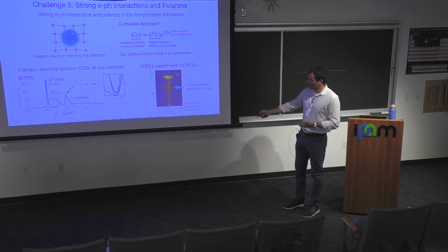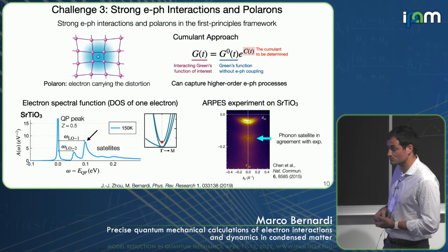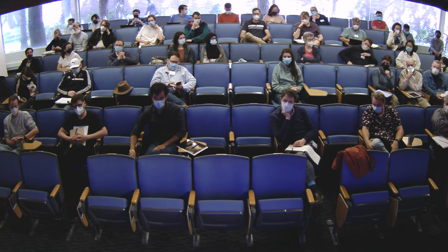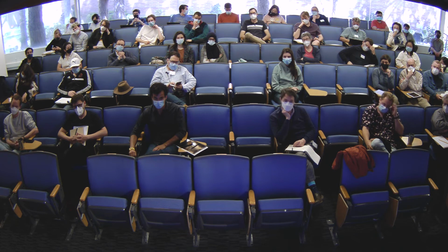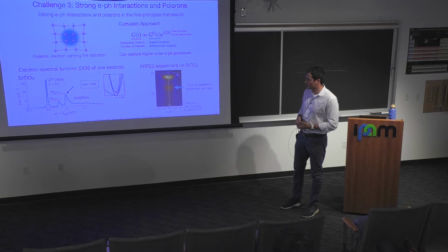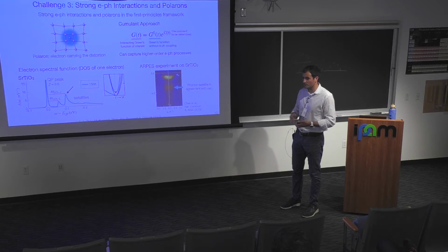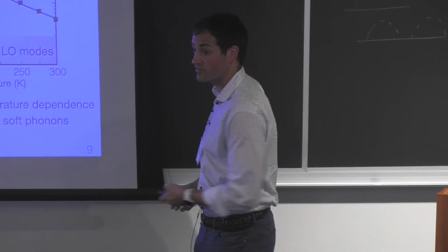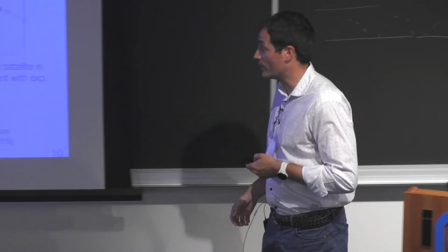But in general, these satellite peaks and their appearance here, this is usually a signature of the polarons. But you cannot really decompose it to see which are actual branches of your phonons that are contributing. This is mainly the LO1 and LO2, because the spacing, in this case, is very clear. We've also done this for organic systems, and there it's really a combination of modes because you have many modes. But for polar systems, it's usually the LO phonons, and we know that they basically have the strongest coupling, so this is kind of expected in a way.